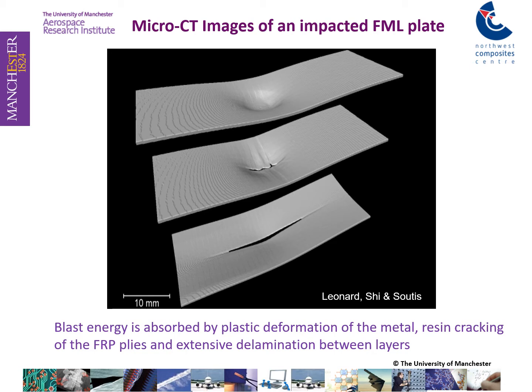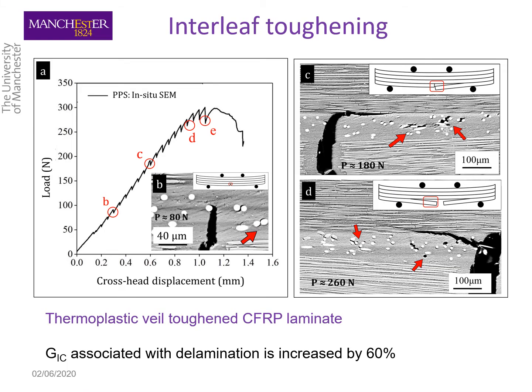And here we have a construction that is tough and accommodates the energy created during the dynamic event. We can make it even harder for the delaminations to initiate by introducing thermoplastic veils at predetermined interfaces. So in this instance, the strain energy release rate associated with the delamination can be increased by 60%. And then the propagation of the delamination finds additional resistance because of the thermoplastic veils.